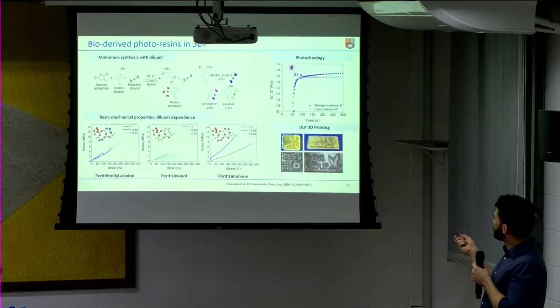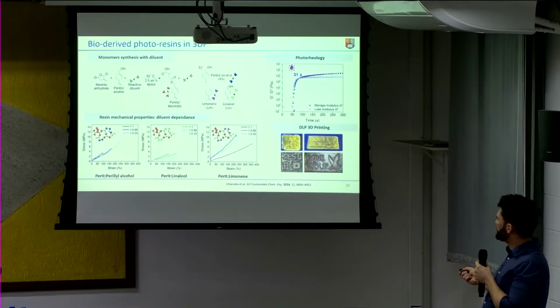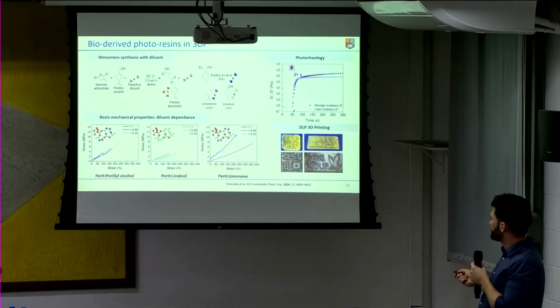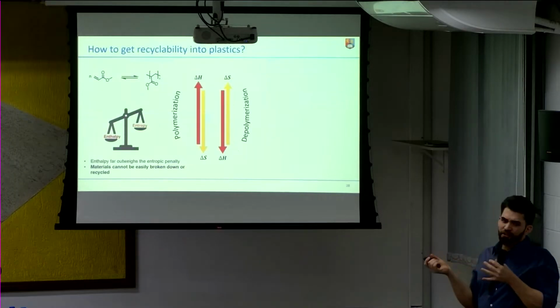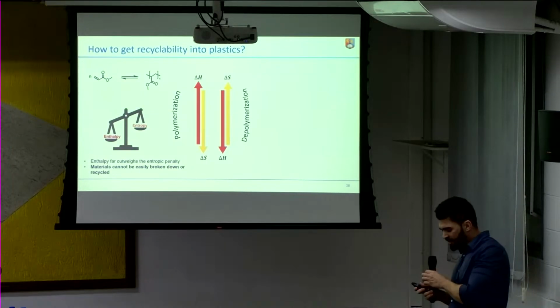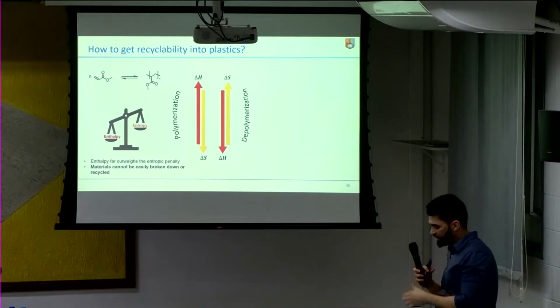And so we ran photorheology to help figure out the parameters for 3D printing. And then we were able to 3D print some constructs. And this is the photo of the printing, and these are the 3D microscopy images that we took, optical microscopy. But this is still not recyclable because those bonds are not going to break so easily.